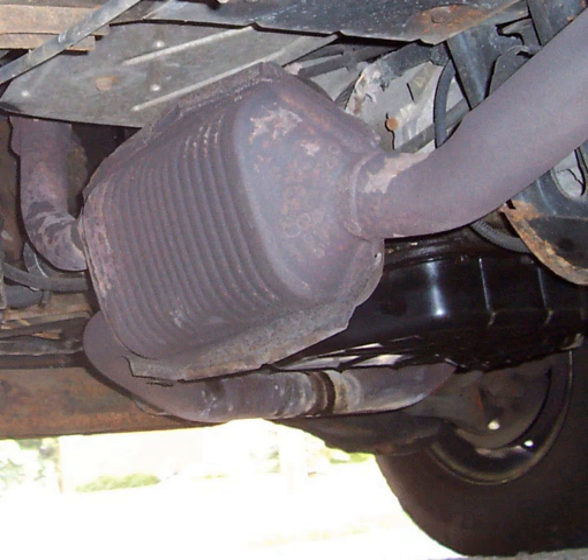Phosphorus is another catalyst contaminant. Although phosphorus is no longer used in gasoline, it and zinc, another low-level catalyst contaminant, were until recently widely used in engine oil anti-wear additives such as zinc dithiophosphate (ZDDP). Beginning in 2004, a limit of phosphorus concentration in engine oils was adopted in the API SM and ILSAC GF-4 specifications. Depending on the contaminant, catalyst poisoning can sometimes be reversed by running the engine under a very heavy load for an extended period of time.